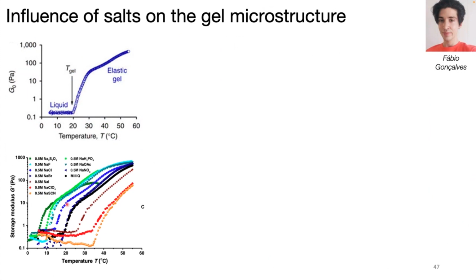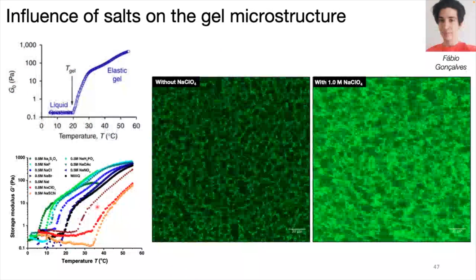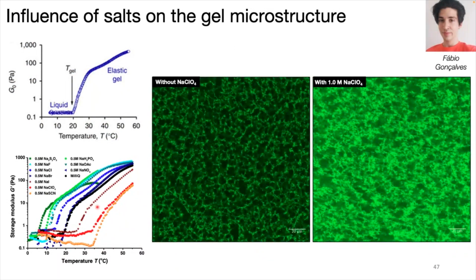And if you look at the mechanical properties, you would say that's the only thing that is happening when we add salts. You are just changing the gelation temperature. But actually, when we look at the microscope, it looks like the structure of the material is also different. So here you have the normal PIC just in water, and then you have here the PIC with 1 molar of sodium perchlorate, and you see that the structure is completely different. The fibers are much brighter, much more dense.